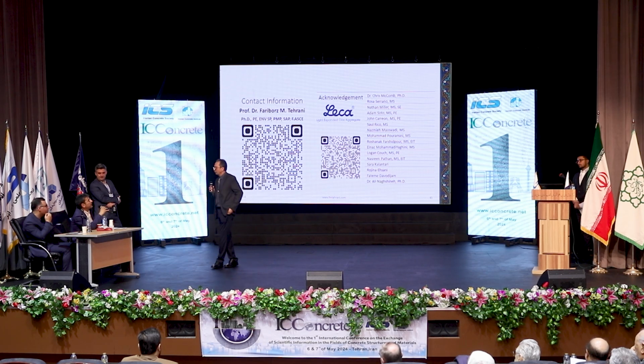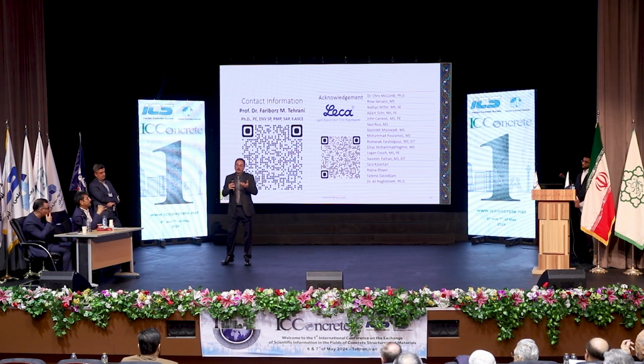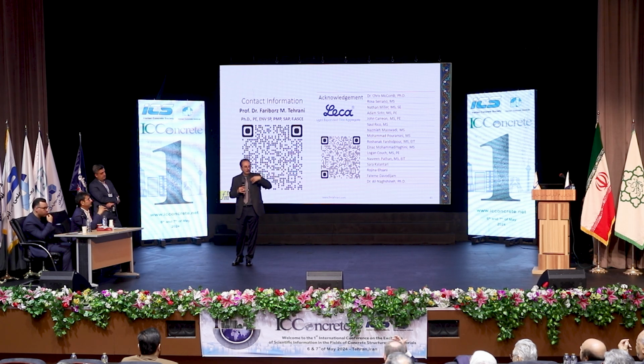You don't propose lightweight aggregate for internal curing for all concrete. You don't want to say that. Yes, I do. Any concrete that's exposed to harsh weather or harsh climate, any concrete that's susceptible to corrosion, yes, I do. But if it's like a skeleton, covered, well protected, if service life doesn't matter, no. That's what my example was, like bridge decks, marine, parking garages, a balcony close to salty air. If it's susceptible to corrosion, yes, I do.